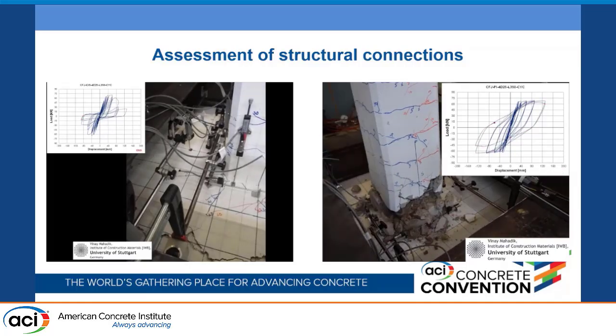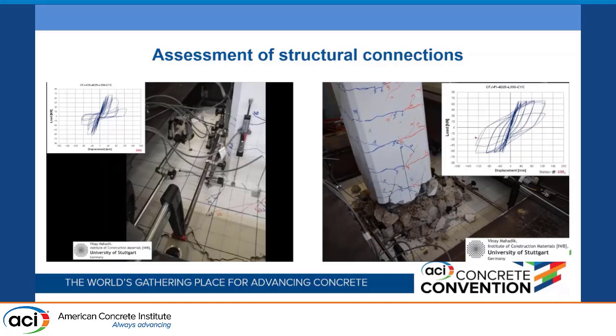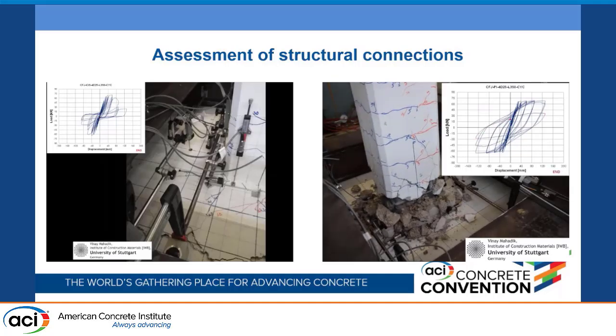We will also see that in the hysteretic loops, after reaching peak, we start to get large pinching, typical of bond pull-out failure, and we have large strength degradation, whereas in case of post-installed, we are able to develop fully formed hysteretic loops, which is due to the steel yielding.